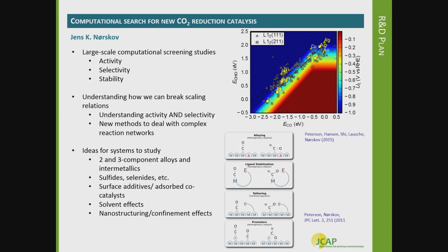And of course, one of the big challenges, as we know from extensive previous effort in CO2 reduction, is that while we have CO2 reduction catalysts that are active and stable, it's very difficult to make them selective, heterogeneous catalysts that are selective. So what we need to do is to break so-called scaling, in which the activity for generation of one product can be regulated and tuned relative to that for another.